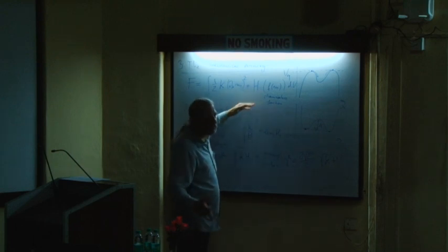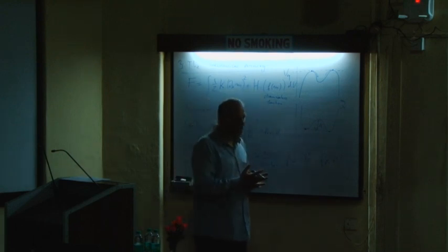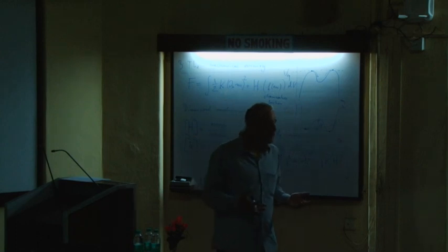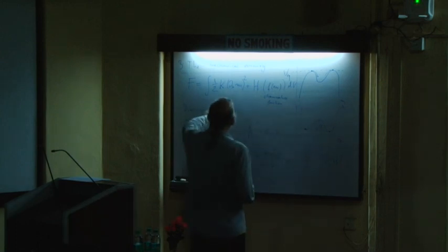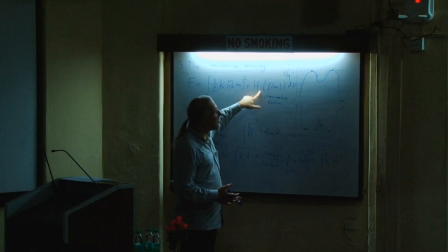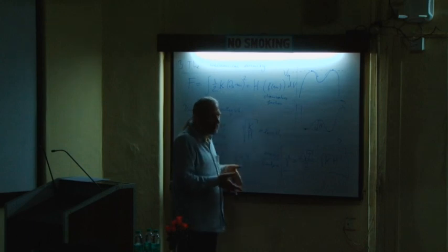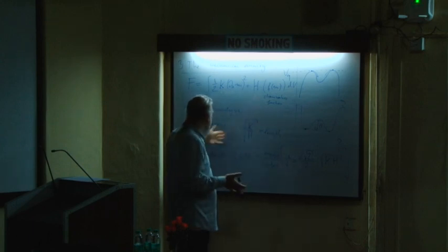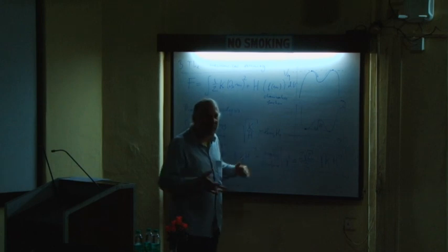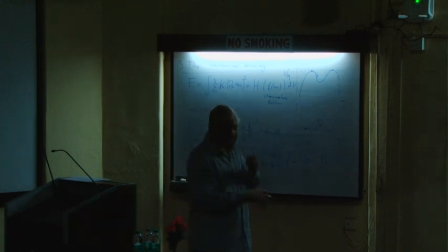This term wants to push it to a step. So in some sense, these are two antagonist terms. This term wants to make the interface wider. This term wants to make the interface sharper. And as a result, you get this diffuse but localized interface, which has this physical scale as its length because it results from two opposing trends.